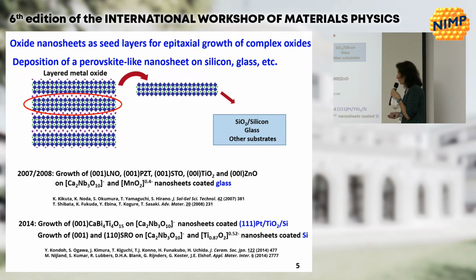Here, I will present to you today another way, which is slightly different, since in this case, we are transferring nanosheets directly on the substrate. It could be any substrate, and this is not a growth of a template layer. This is an exfoliation of a layered metal oxide, which is a parent compound, and all this process can be done at room temperature.